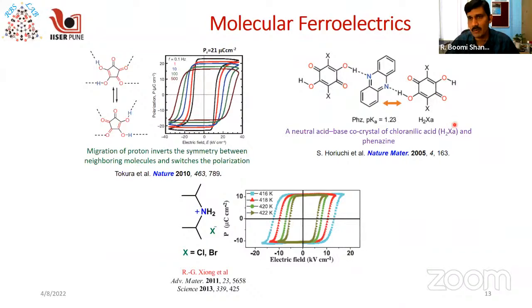Then people worked on simple acid-base co-crystals. This is a neutral acid-base co-crystal of phenazine and chloranilic acid. Here also the proton migration was found to be responsible for the ferroelectric polarization, because the proton switches between two states, giving rise to the two polarization directions.